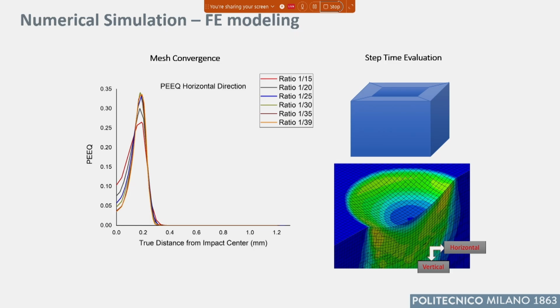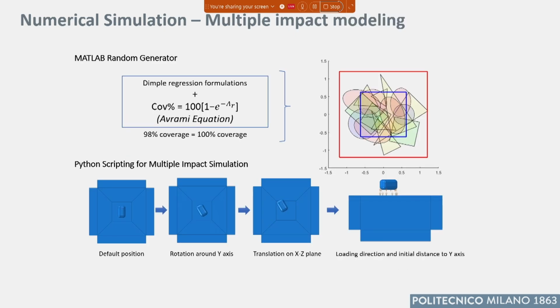These are the resulting PEEQ, the equivalent plastic strain, considering the different shots. Here we are evaluating the step time. And this is the way a complete cycle is performed. Finally, if we want to reach full coverage, we have to apply the classical Avrami equation, which makes it possible to calculate how many impacts we need for 100% coverage. This is what is done here, and a Python code has been developed to assess these conditions.